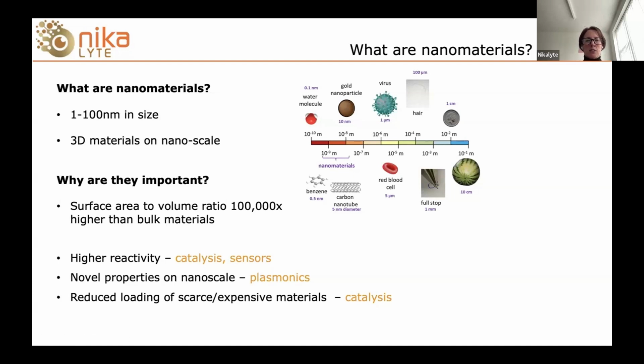And what makes them really interesting? Why are there so many people looking at nanomaterials? One of the key reasons is their surface area to volume ratio. When you get down to the nanoscale, what you're looking at is a massive increase in the ratio of the surface area to volume, by several orders of magnitude. And what this means is that the surface becomes really, really important at this scale. The knock-on effect for applications is higher reactivity for applications such as catalysis and sensors, which is obviously very important in those areas.